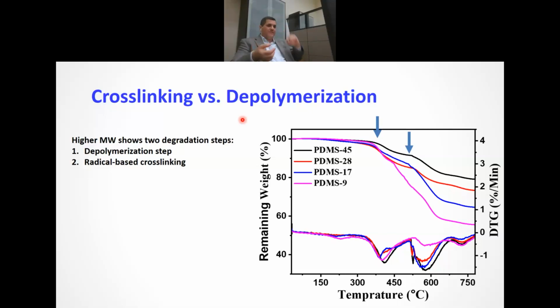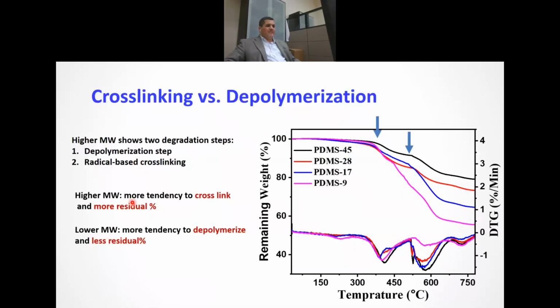So through the discussion with Dr. Ayman, Dr. Rifat, and the rest of the colleagues, we thought, okay, there are two things going on there in terms of mechanism. There is a degradation that happens through a depolymerization step or a radical cross-linking step. So the high molecular weight, sorry, has more tendency to do two different steps through what is called the radical-based cross-linking. In terms of the radical-based cross-linking, what's happening is